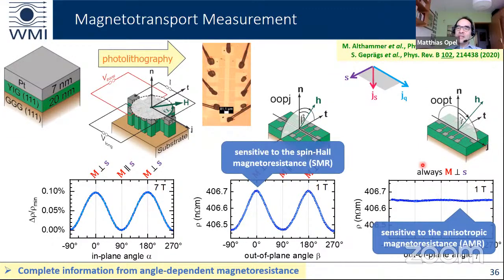So this geometry here is not sensitive to the SMR effect, but it would be sensitive to the anisotropic magnetic resistance, the AMR effect. This geometry is not sensitive to the AMR, but it is purely sensitive to the SMR effect.